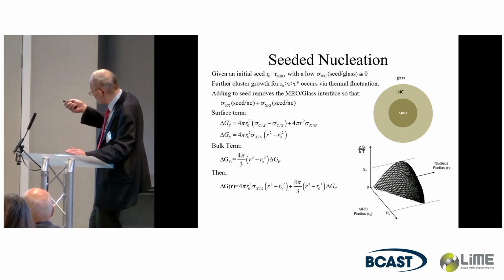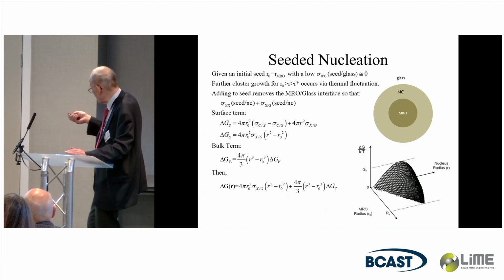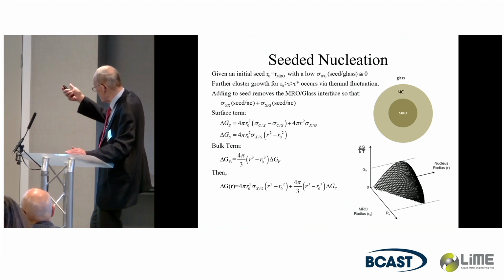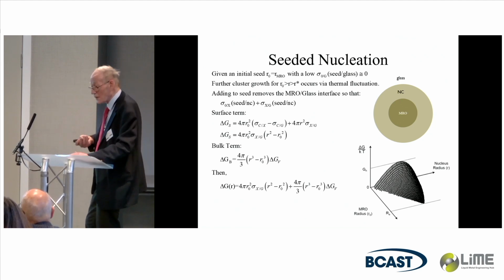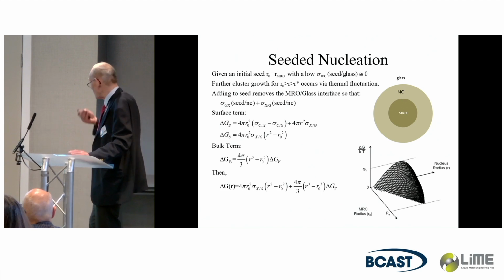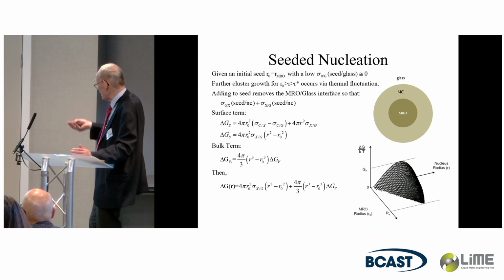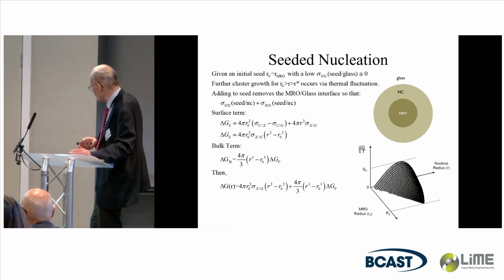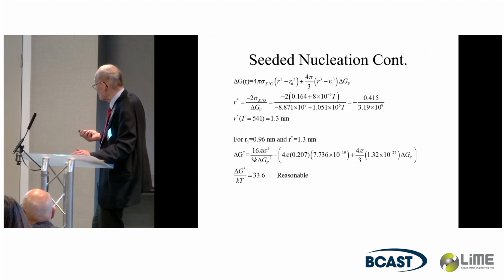And with this, you replace those interfaces. And because the MRO takes up part of the volume, it's a very effective heterogeneous nucleation site. And it's chemically the same as the nanocrystal. So we have complete wetting. So it acts as a very good seed.